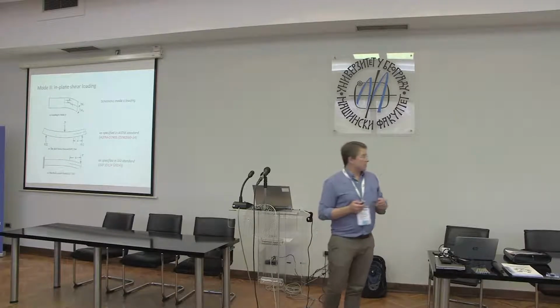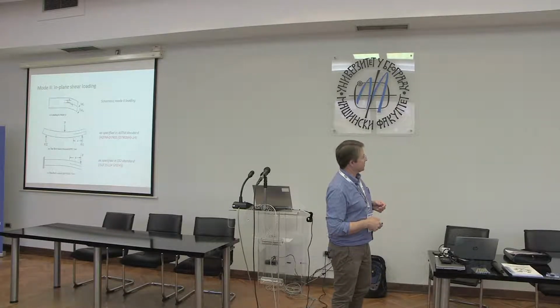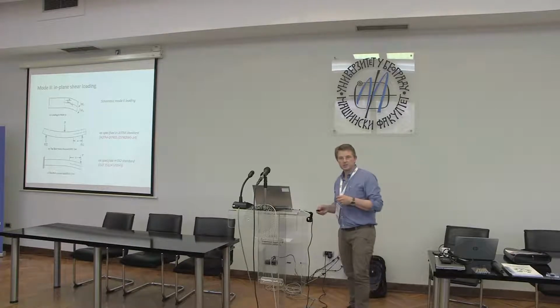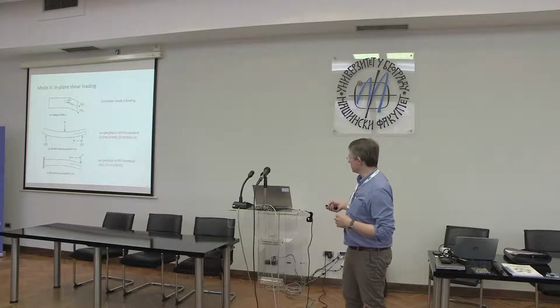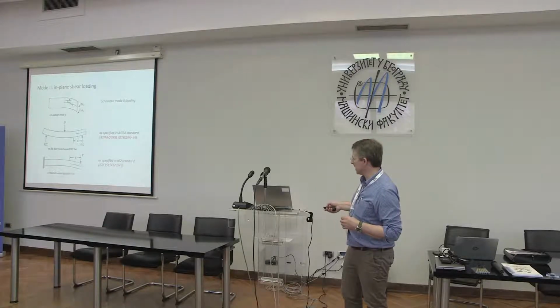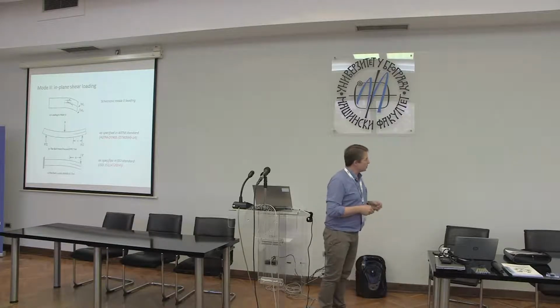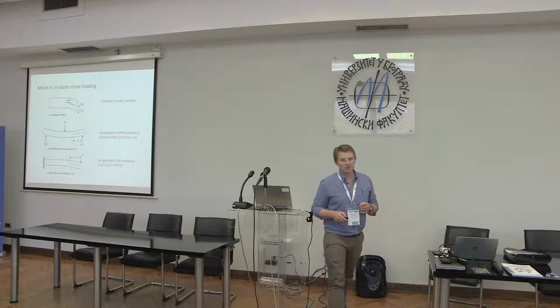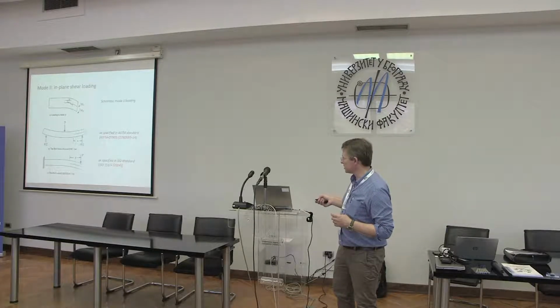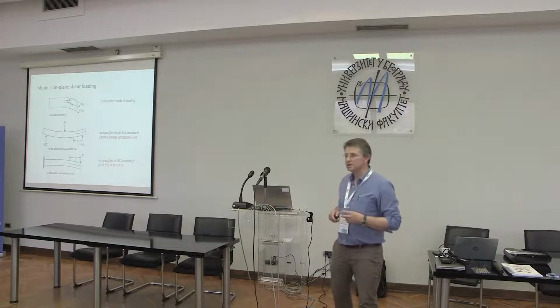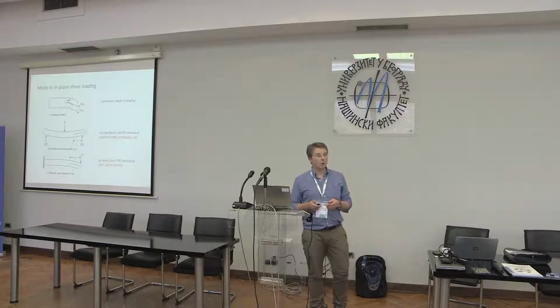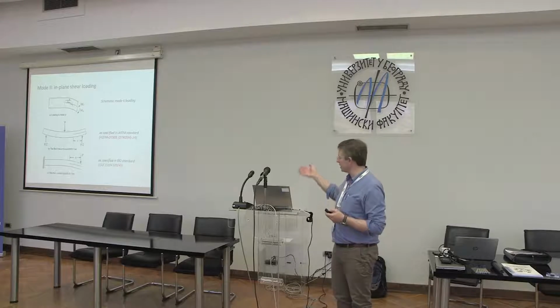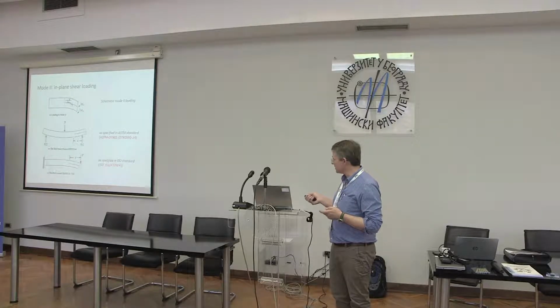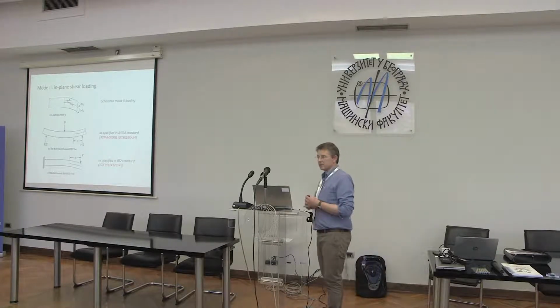The ASTM group have preferred a 3-point bend version of this, which is then described as the end-notched flexure test. It's end-notched, you can see, and it's a flexure test, whereas the ESIS group has preferred the ELS version of this experiment, which stands for the end-loaded split. And this is a cantilever clamped at one end. So you can see there are complications of the clamp. But the advantage of the clamped system is that it has better stability profile than the free system. The free system, the ENF system, tends to suffer from more instability. So if you're performing this experiment, it's more likely that the crack will go unstable and will run straight to the centre of the sample following crack initiation.